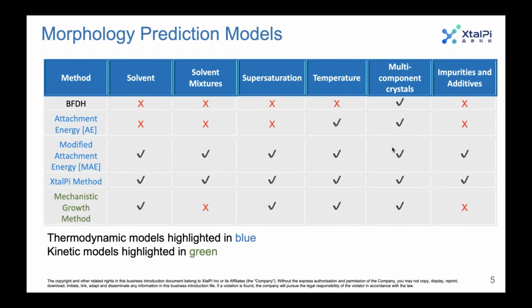Okay. The next question is from Shenglin Zhu. The question is, in morphology prediction, how is the mass transportation considered in the model when the kinetics of different phases may be limited by this transportation? That's a good question. So again, this is the thermodynamic model, not a kinetic model. So we're not really taking any kinetics at all into account. This is an equilibrium model where we're basically getting the growth rate by determining the equilibrium between the surface and the API molecules in the solvent. I'm wondering if, based on the trajectories of the simulation, we could give any sort of insight into that. I think we'll have to get back to you on that question after thinking about it carefully.